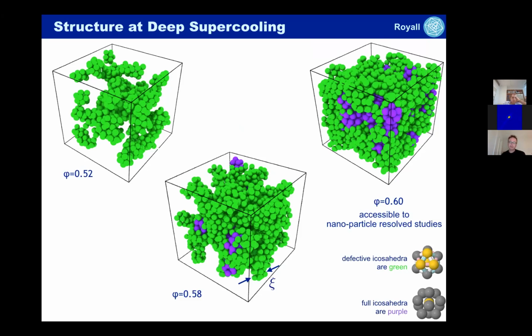With colloids, though, we increase the volume fraction, which we denote with phi, rather than reducing the temperature, but it comes to the same thing. So increasing phi takes us towards the colloidal glass. With 0.52 volume fraction, we have some particles in defective icosahedra, which is the local structure for this system. As we increase the volume fraction, we get more and more particles in the relevant local structure, so that by a volume fraction of 0.6, almost all the system is in a local structure.